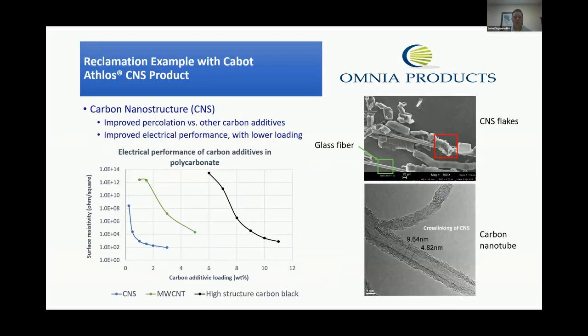Okay, so this leads us to today's example. We work with Cabot Corporation. They have a very interesting product. It's a CNS or carbon nanostructure material, which they have trademarked as Athlos. And here in the picture on the right, you can see in the red box would be the CNS material that has actually been grown on a substrate, which is the glass fiber. So glass fiber is highlighted in the green box. If you zoom in closer, you can see actually the branching structure of the CNS material in the lower image. So very interesting material.